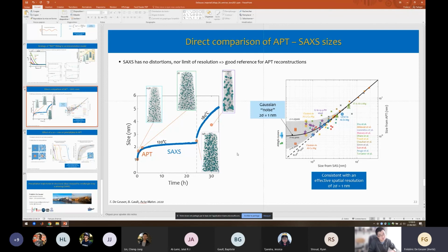So it's important to keep this in mind when working with this, because again, this is noise. This is a shuffling of the atoms. It doesn't mean you don't detect clusters. It means you shuffle them. So you need to keep in mind what that does. If you have a very small cluster, you will still detect it, but it will look much broader and much less concentrated. So you just need to keep this in mind when analyzing.